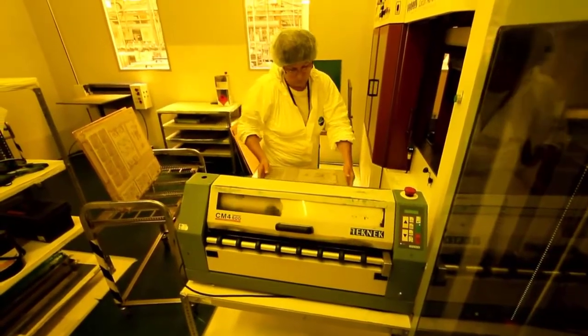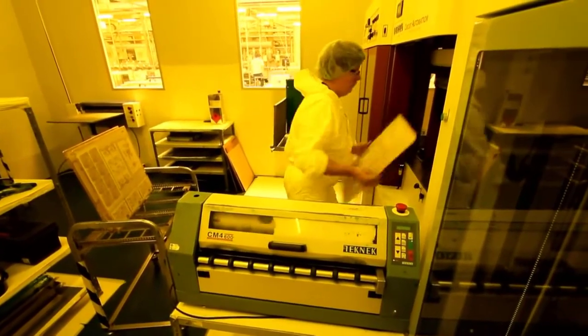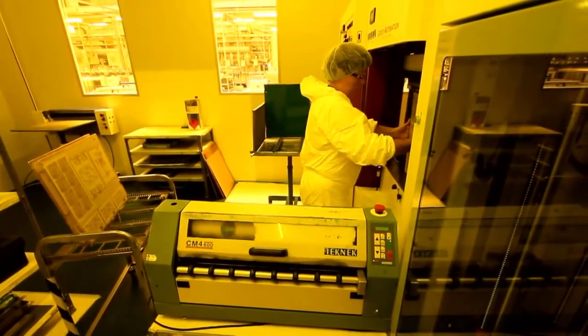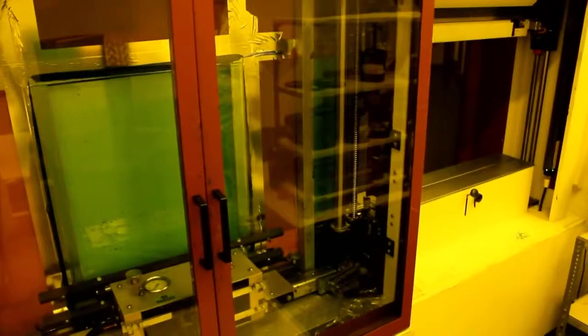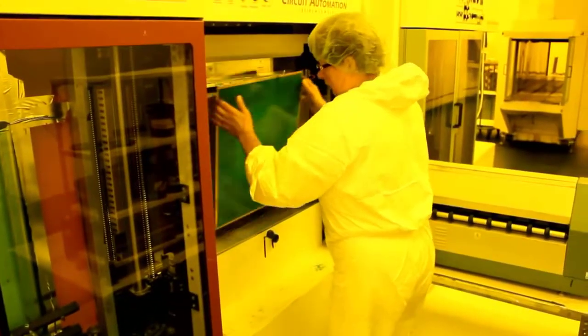The coating machine simultaneously covers both sides of the panel with the epoxy solder mask ink. The double action ensures that the ink completely encapsulates the copper tracking, typically now 35 to 40 microns higher than the surface of the panel. The panels are now racked and put through a conveyorized dryer which hardens the resist just enough to allow it to be printed, or tack dried. The operator checks for a complete and even coating.